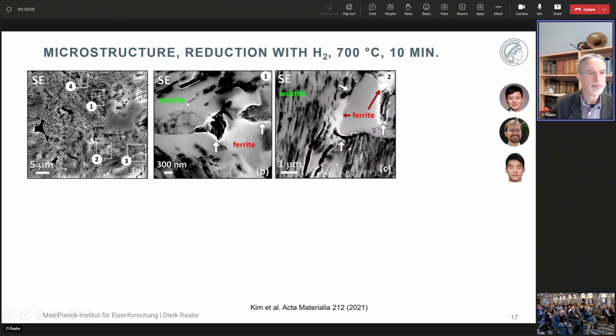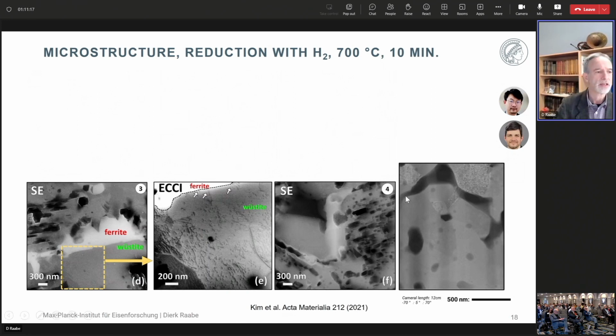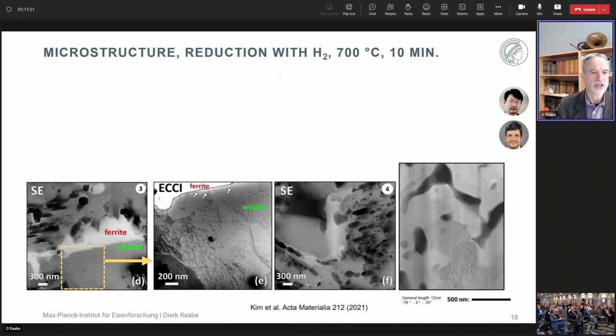When we jump a little bit deeper into the microstructure, you can see that not everywhere we have scenarios where the wüstite, like here in gray appearing, is completely surrounded by the bright appearing ferrite, but you have delamination and you have fracture, maybe even supported by hydrogen, I don't know. But you have also an opening up of free new volume due to the massive volume changes, which is very important to understand finally the kinetics of these processes. You also build up GNDs, like you see in the channeling contrast here and so on. So it's very rich in microstructure, which is in part due not just to the mass loss, which is thermodynamic, but also due to the huge stresses between the adjacent phases.